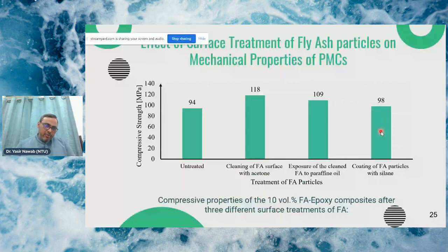I have added only one example, for compressive strength. If we do different surface treatments, like cleaning with acetone, then treatment with paraffin oil, then the silane coupling treatment, so only with the cleaning of the surface, we get good wettability, and the proof of that is that the compressive strength is increased significantly. So it means by proper dispersion, by proper cleaning of fly ash, we can add these particles to the composites, whether they are thermosets or thermoplastics.